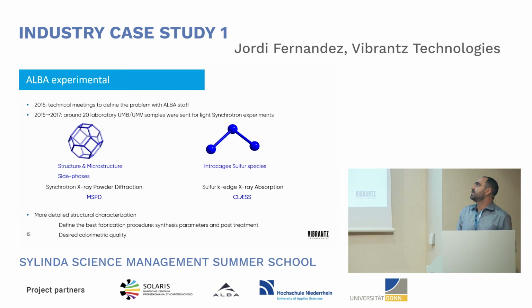So, as I told you, in 2015 we contacted ALBA, and we did some technical meetings to define the problem with the experts at ALBA, and then from 2015 to 2017 we sent several samples to be analyzed in these two lines. First in the MSPD to run synchrotron X-ray powder diffraction studies, trying to have a good adjustment of the structure and microstructure of our pigments, and also the presence of secondary phases, because many times the secondary phases are less than 2% in composition. So with conventional techniques, sometimes we are not getting this information.